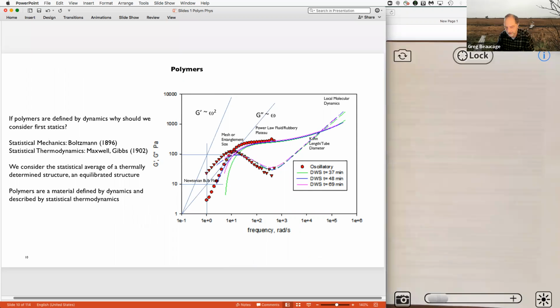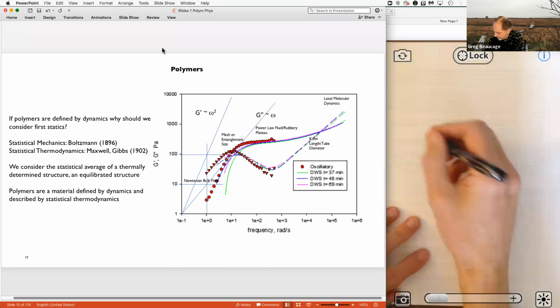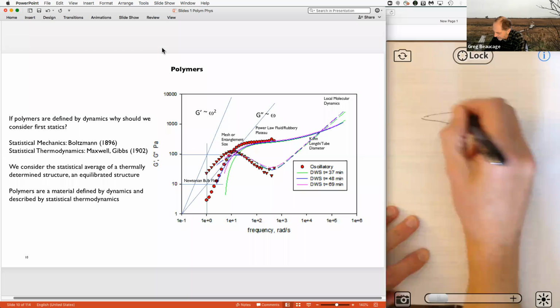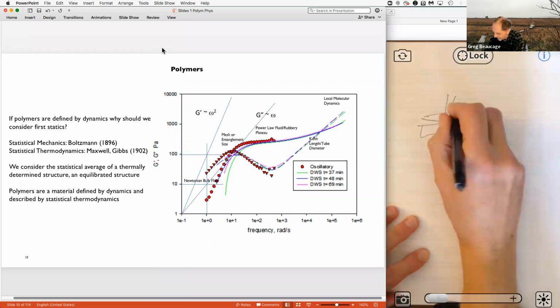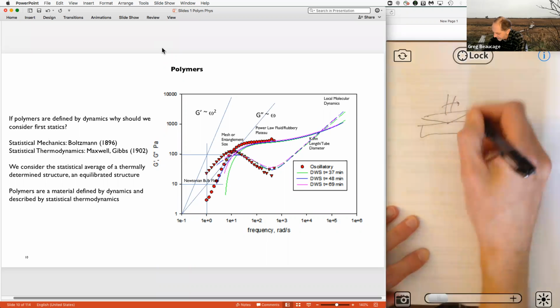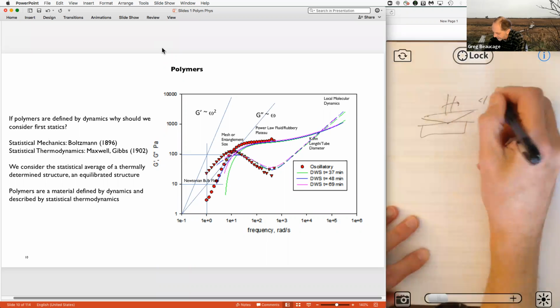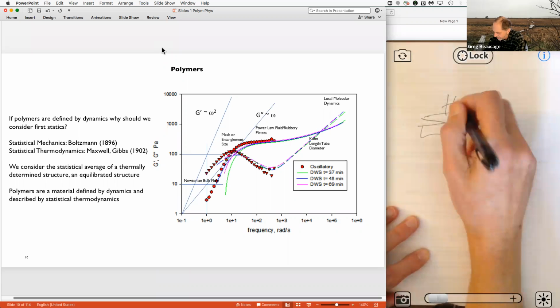So this is a dynamic viscometer measurement, and ideally you're going to have a cone and plate setup, right? I think I showed you some of these. This is going to be oscillating, right? And the strain is going to be less than 1%.